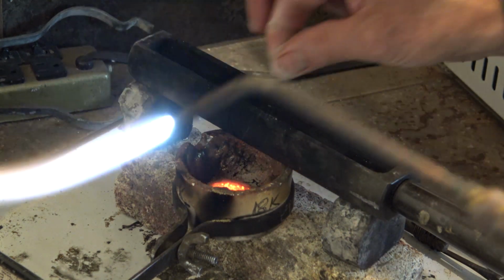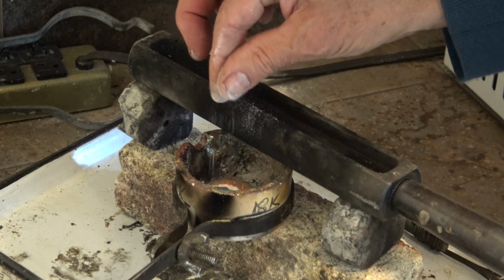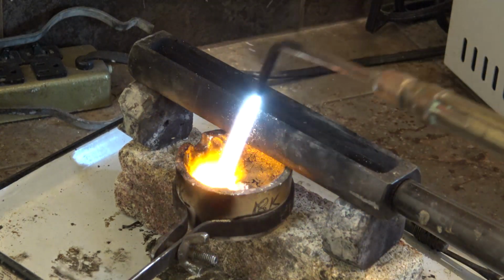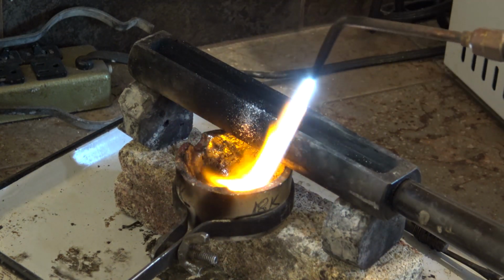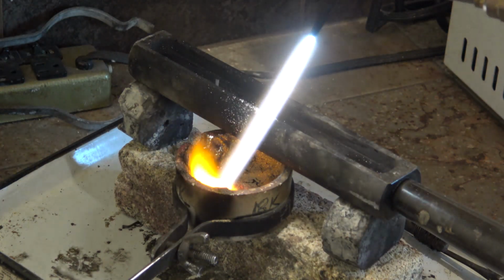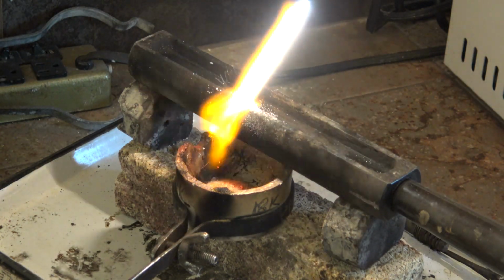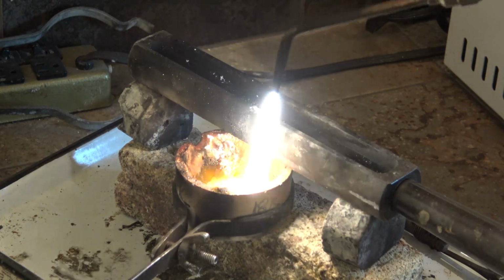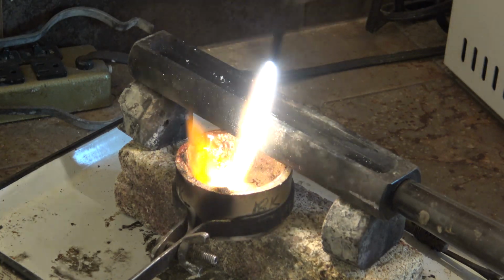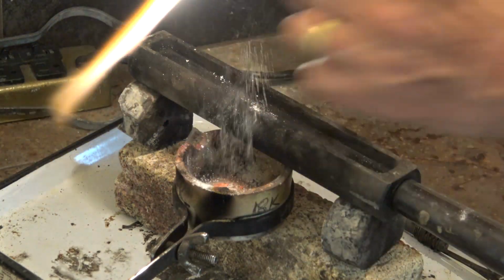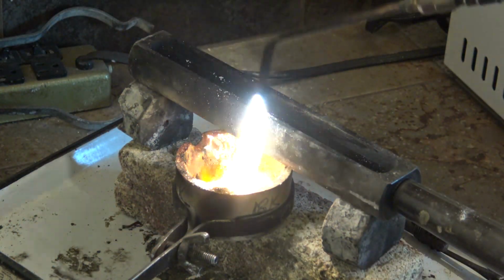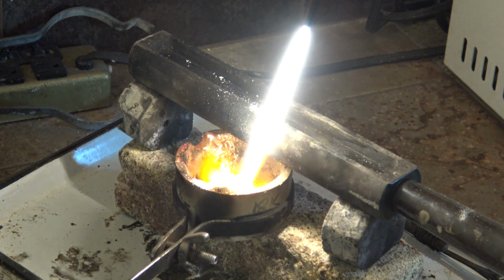I let a crust form on the top of the filings and then sprinkle a pretty liberal amount of borax. And then I increase the flame slightly so it's a little bit hotter and blowing a little bit harder. Now that there's a crust on top, the filings don't blow away as easily. I'm again adding lots of borax. Increasing the flame again.